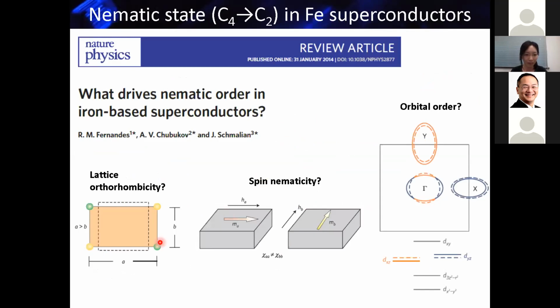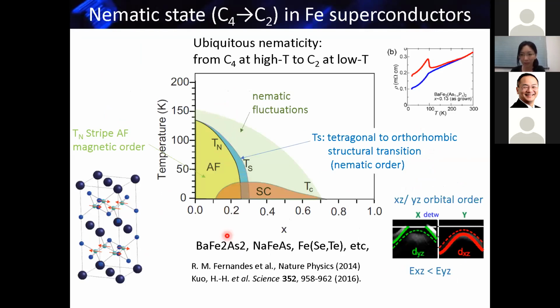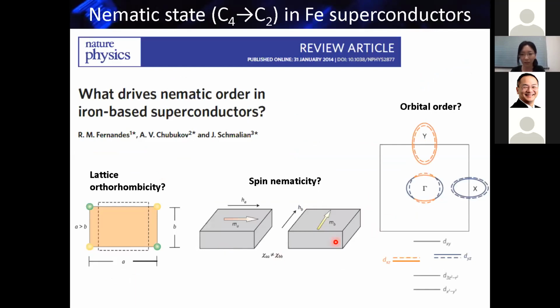There are many discussions on this nematic state, but as I already stated, there are too many players involved in this nematic order. One is the lattice, from tetragonal to orthorhombic, and spin nematicity, which is also coupled to the antiferromagnetic phase. And as I told you, there's orbital order, Xz and Yz. So orbital, spin and lattice, there are many players, and as you can see in the title of this paper, it's very difficult to say who is driving this nematic order, because these transitions occur almost at the same time when you cool the temperature. Who drives whom is very difficult to pin down.